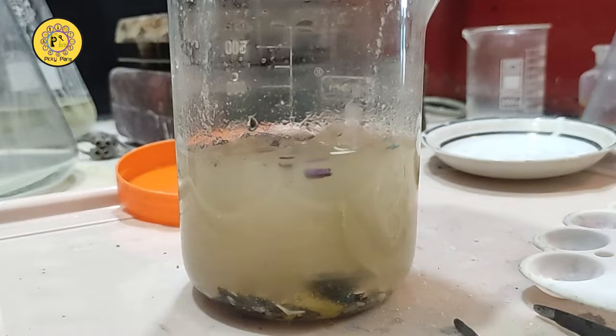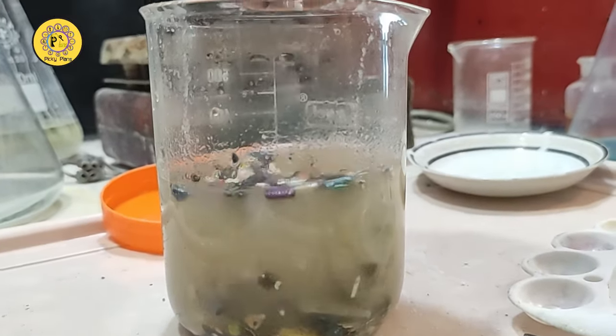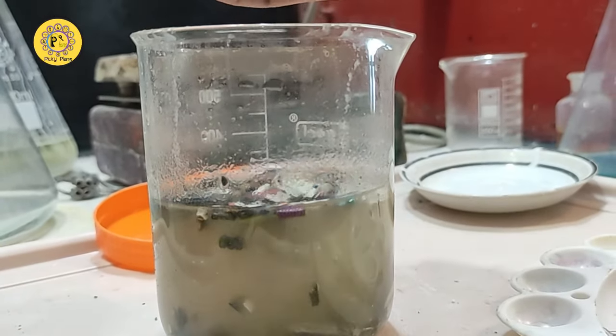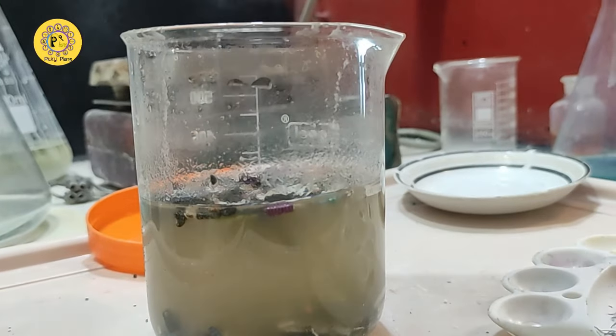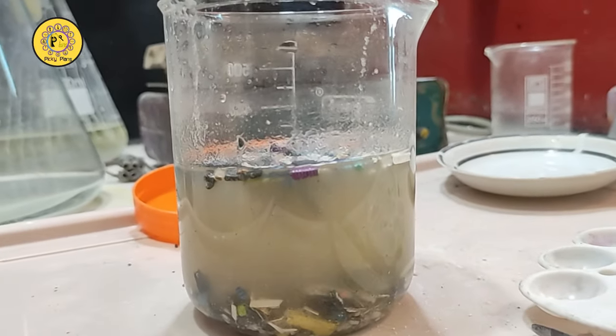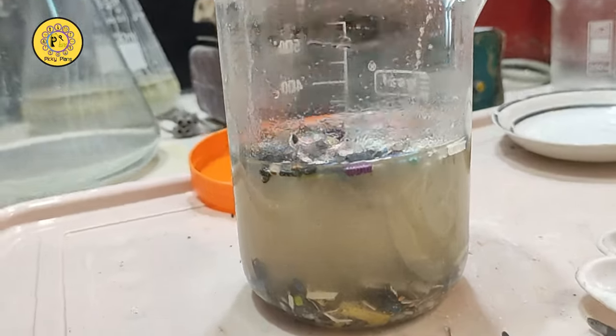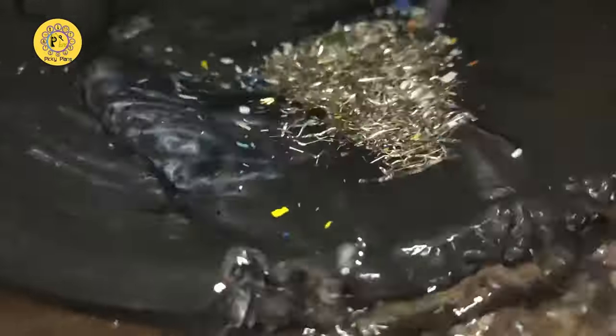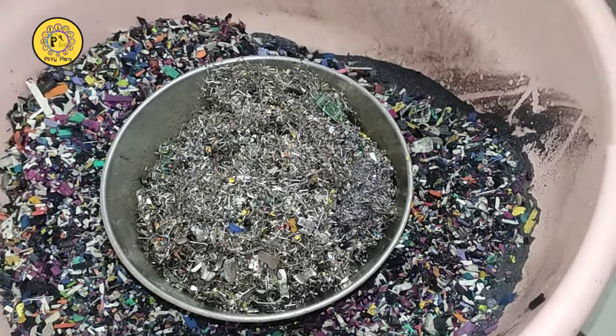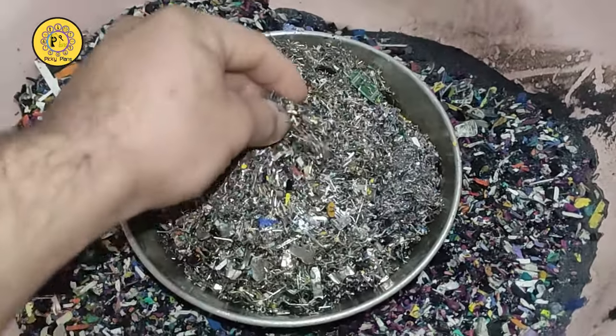I tried to separate the metallic fraction from the plastic through flotation in saturated magnesium sulfate solution, but it seems it wasn't successful for all plastics. So I decided to use my pan to wash the plastic out. As a result, almost clean pins with the plastic removed.